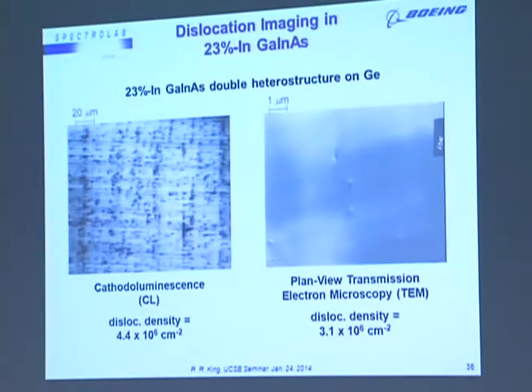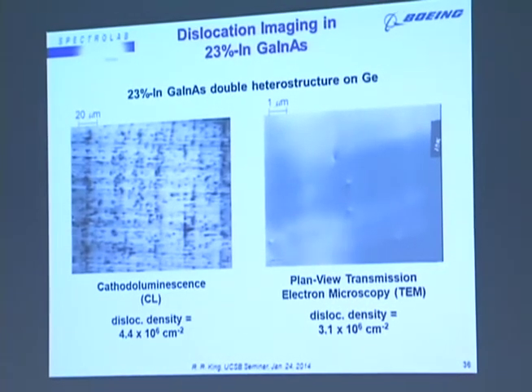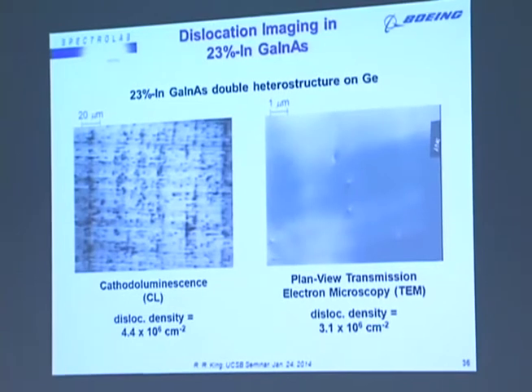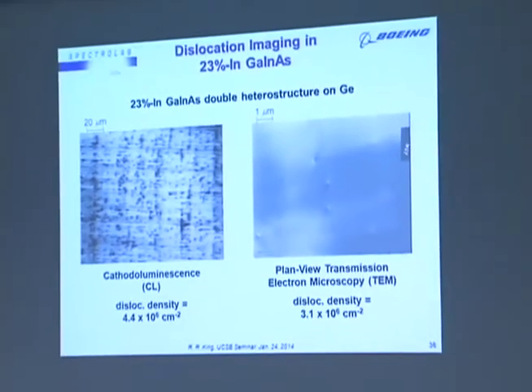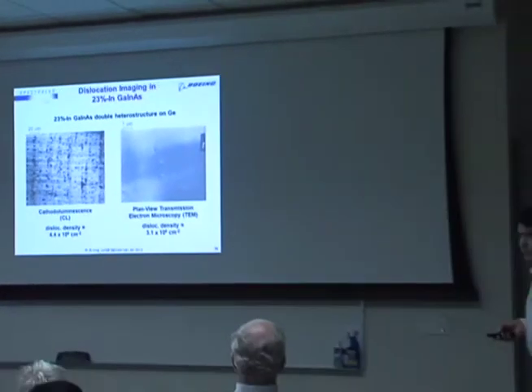Some more examples of characterization in this 23% or about 1.1 eV gallium indium arsenide. We image defects with cathodoluminescence and also with plan view transmission electron microscopy. Both are giving pretty good agreement of dislocation densities in the 3 to 4 times 10 to the 6 range for this composition. So it's encouraging that these are agreeing with each other.